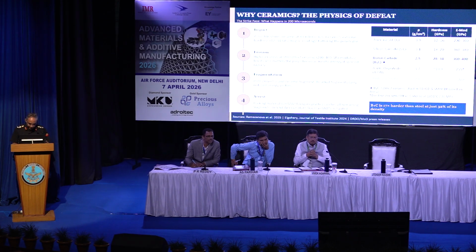There are 4 steps into it. I'll just briefly touch upon them. First is the impact. The ceramic phase with a Vickers hardness of 28 to 34 gigapascal immediately begins to erode the hardened steel core of the projectile. The ceramic is harder than the penetrator. That is the first and foremost critical fact.